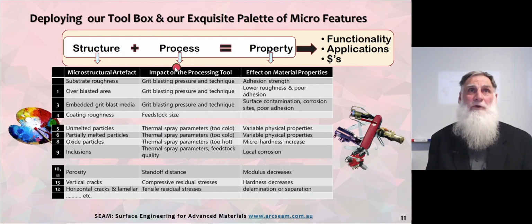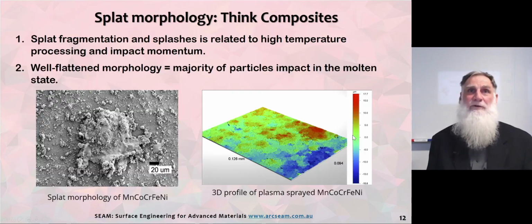So we have a toolbox. We have a toolbox and a palette of micro features. So we have a structure. The microstructural artifacts could be over-blasted areas, embedded grit blasted, coating roughness, unmelted particles, giving rise to all of these artifacts. And we include porosity, vertical cracks, horizontal cracks. We have a process, so we have the impact of the processing tool, which could be grit blasting, the feedstock size, the thermal spray parameters, the standoff distance, and other factors. And then finally, we have the property. The structure and the process influence the property: adhesion strength, low roughness and poor adhesion, variable physical properties, micro-hardness properties. All of these material properties eventually give rise to the functionality of the overall coating, hence applications and the commercial incentives. So we have a palette and we have a toolbox, and that gives rise to applications.